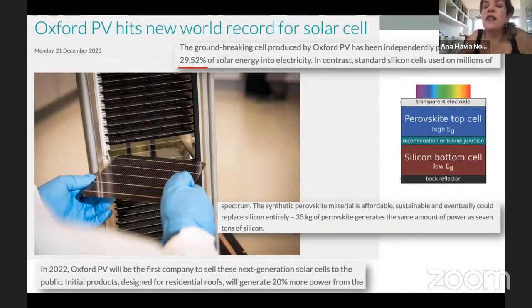So this is also a question: when are we going to see perovskite solar cells in the market? This is one of the companies, Oxford PV, created by Professor Henry Snaith, although the factory is actually in Germany. I just checked the website yesterday, and they still claim that this year they are going to be the first company to sell what we call tandem solar cells. What is a tandem? As you can see here, a tandem is when you have two different photovoltaic cells together in order to increase the absorption of light. So you have the silicon solar cell at the bottom, and then you put the perovskite solar cell on the top. With the tandem, you can increase your efficiency close to 30%.